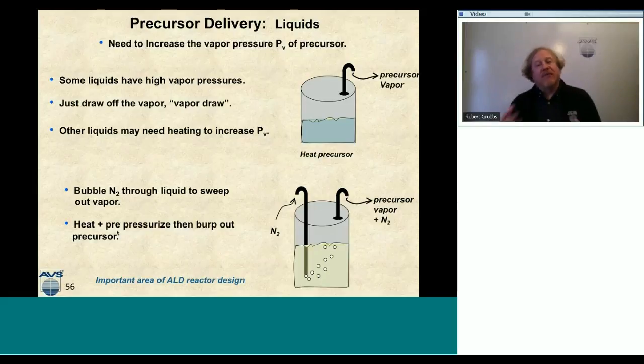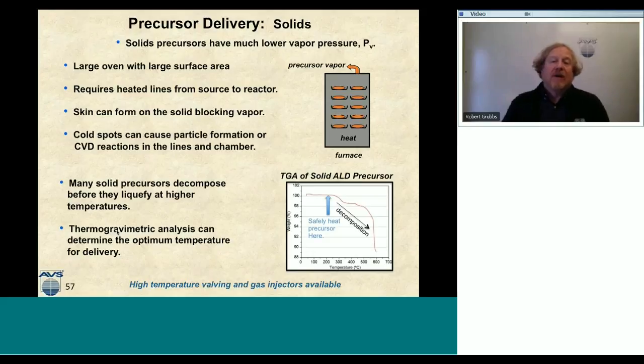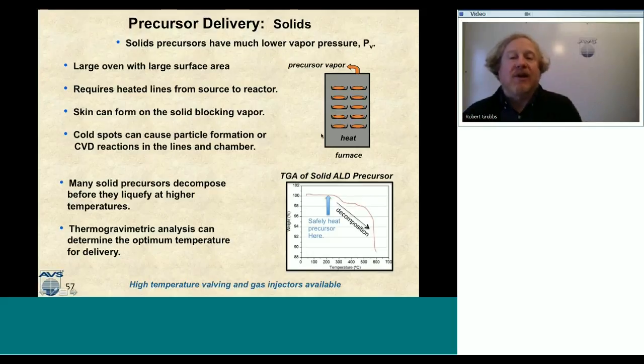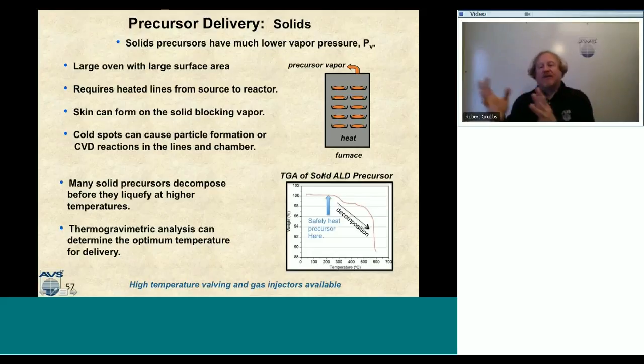Now, solids are a different beast, and they obviously have much lower vapor pressure. One of the ways you can deliver them is with a large oven with all these little trays of your solid, just to get the sheer number of atoms into the vapor, since the vapor pressure is low. You'd heat it, attach this furnace essentially to your reactor, and that would be your precursor source.